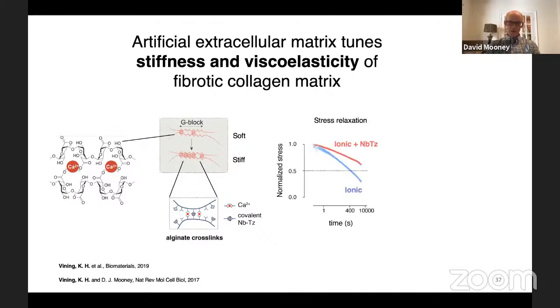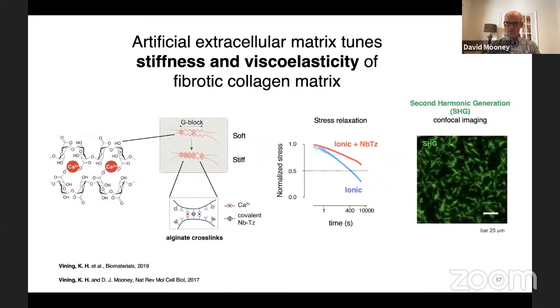By this, he could create materials that would have varying rates of viscoelasticity, as indicated by varying rates of stress relaxation, without changing any of the other features of the system, such as the collagen fibril formation, the mesh size or porosity of the gels, or other features.